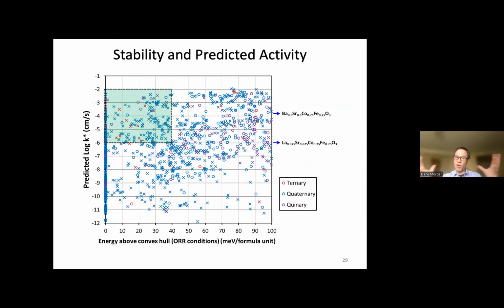So here's the list of all the calculations. Here's our surface exchange coefficients on the left axis, our stability on the x-axis. And we got our couple of thousand calculations, and the stuff we're really interested in is this region up here in the top left corner. This is highly stable because it's very close to the convex hull. Even on the convex hull, that gives us a 0 value of instability. Convex hull basically measures how close you are to stable. If you're on the convex hull, you're stable. If you're near the convex hull, you are likely very close to stable. And then high surface exchange coefficient is high up here on this axis.